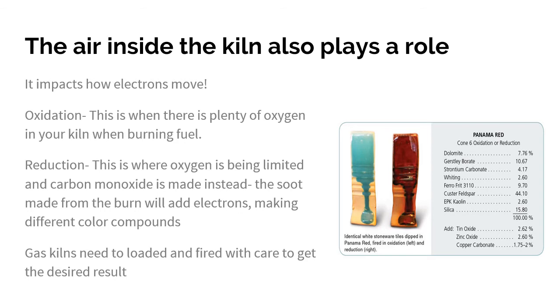I've loaded gas kilns in my studies, and it's very critical how closely you place the pieces together, where you place them in the kiln, and how close they are to any sort of vent that would allow the exchange of oxygen into that kiln. So, artists know their kilns and get very experienced in trying to get the results they want. And you can also intentionally make pieces where maybe one side is more oxidized and one side is more reduced, depending on airflow inside that kiln. So there really is a lot of artistry in this chemistry.